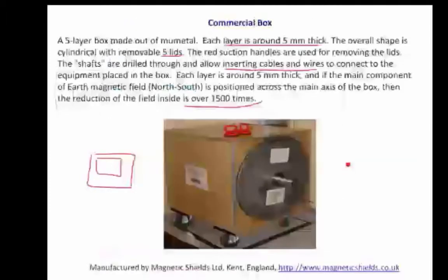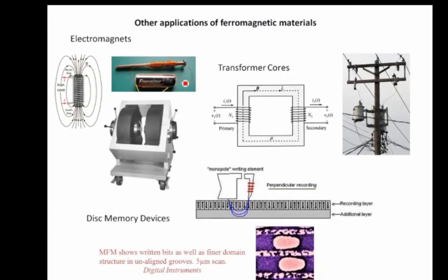There are other applications. If you remember as a kid you made electromagnets, so here's a nail with a coil, so this would be analogous to a solenoid, and you put a battery around it, and because of the material you have here, you don't have very much residual magnetism. So in other words, you magnetize it. If this is the 0 here, didn't quite hit it. But as you go up and down, it goes through 0 approximately. So in other words, this curve is extremely narrow, like that. So you don't have much residual B.